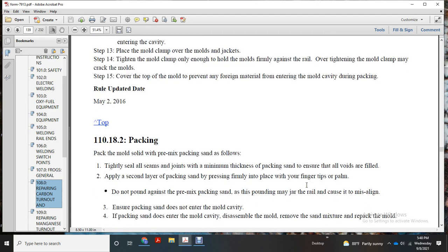Alright, packing. Pack the mold solid with the premixed packing sand. Tightly seal all the seam joints with a minimum thickness of packing sand. Ensure that all the voids are filled. Apply a second layer of packing sand, pressing firmly into place with your fingertips into the palm. Do not pound the premixed packing sand. Pounding may jar the rail, causing it to misalign.